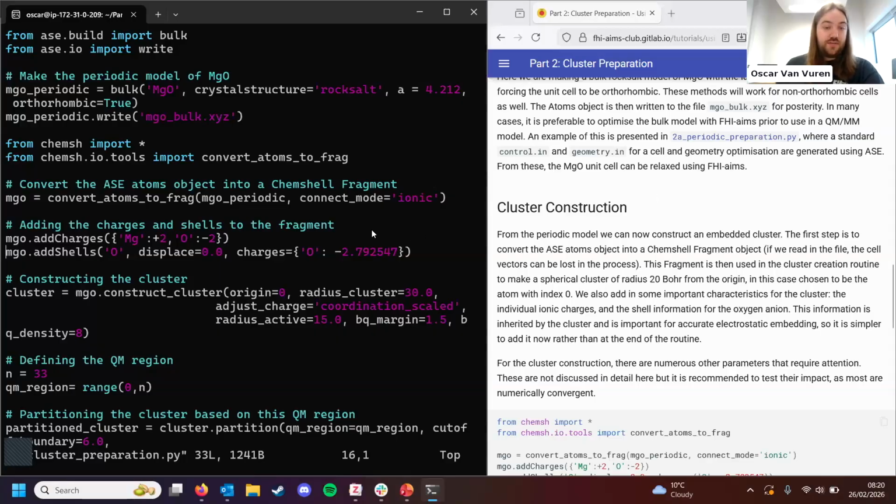So what we do is we add a fitted charge over the top, and the sum of the oxygen core and shell, you can think of it as potentially something like a core and valence electrons, should sum to the formal charge. So the core of this will have a positive charge of 0.79, and the shell has this negative charge. So overall, the ion remains O2 minus formally, but it allows for the polarization. So then once that's done, we've set up our geometry properly.